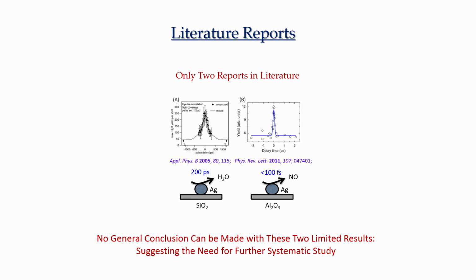If we look at the literature, then we find that there are mostly two works which have been documented, one work was done near about 2005, another work was done in 2011. In 2005 the work was based on the water desorption from the silver nanoparticle, and it was found that 200 picosecond was the time scale for the water desorption from silver nanoparticle.